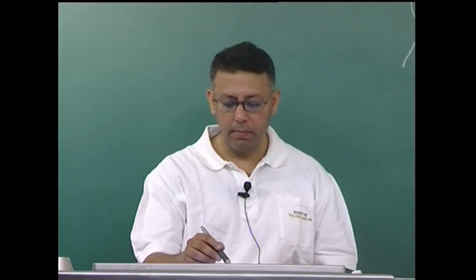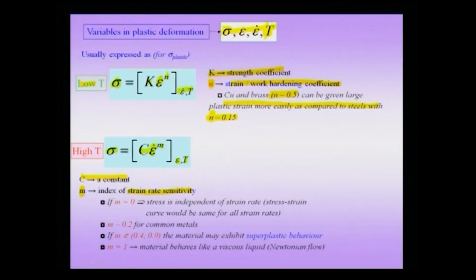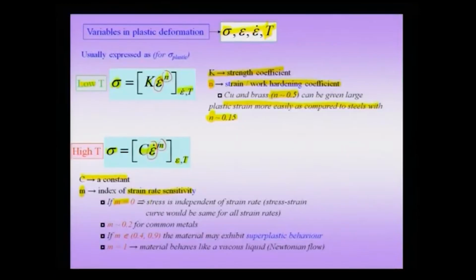This is very similar to n for low temperature tests. In low temperature, the important variable is strain and the important exponent is the strain hardening exponent. At high temperature, it is the strain rate which is the important variable, and it is the strain rate sensitivity which is the important exponent. If m has a large value, then you would expect a behavior at high temperature which is similar to n having a higher value in the case of low temperature deformation. If m is equal to 0, that implies the stress is independent of strain rate, and the curve would be the same for all strain rates. If m is higher, and typically for metals it has a value of about 0.2, then you expect that the material would strain rate harden more compared to a material with lower strain rate sensitivity.